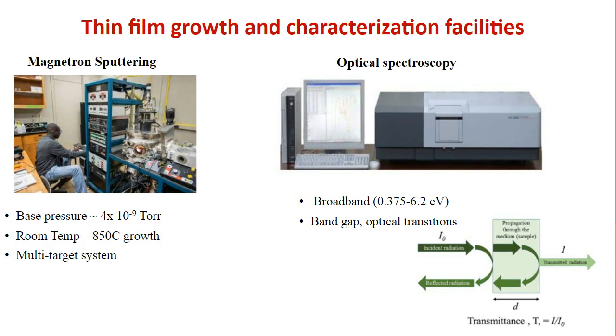So in my lab, I had this magnetron sputtering thin film growth facility. Some of you might be familiar with magnetron sputtering. You take a target, you bombard it with highly energetic argon ions and sputter away some of the material, and it diffuses and deposits on a substrate which is lying a couple of inches or 3 inches away. And if you have the sample at a high temperature, it can grow epitaxially or in single crystal form, and also you can layer it with other materials. So magnetron sputtering is an industry standard. It's also used in the optical industry when you coat mirrors and glasses, right? So sputtering is the way to grow large area thin films.